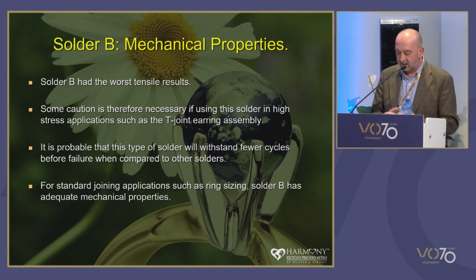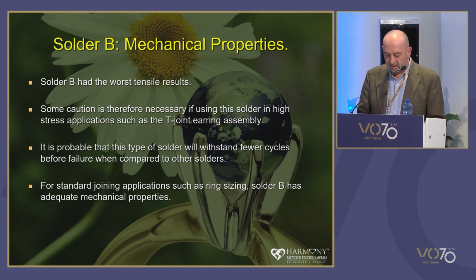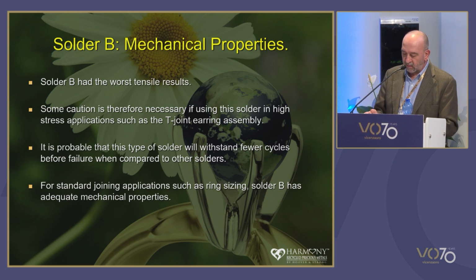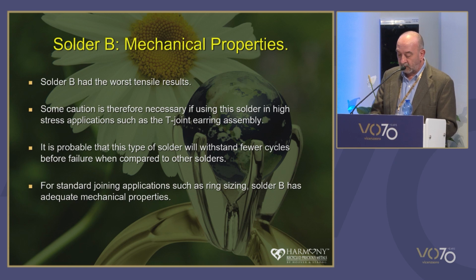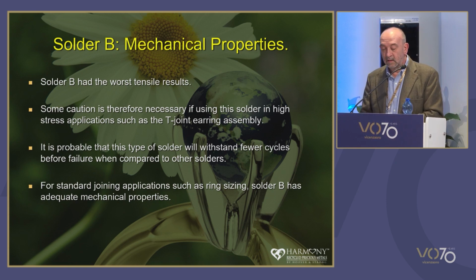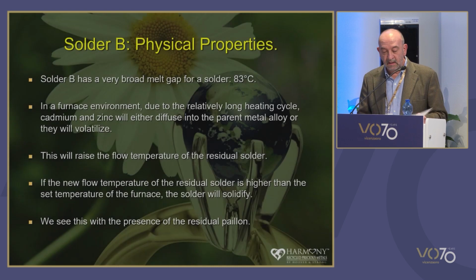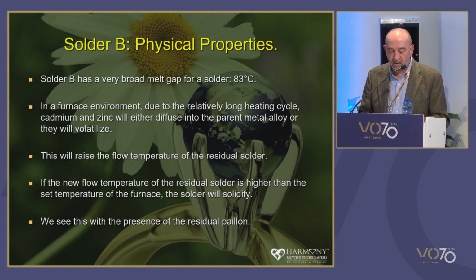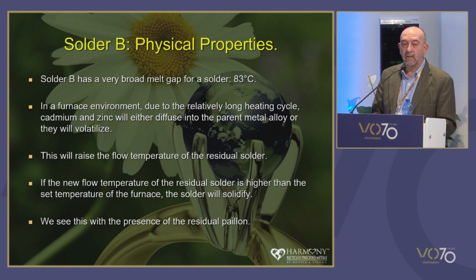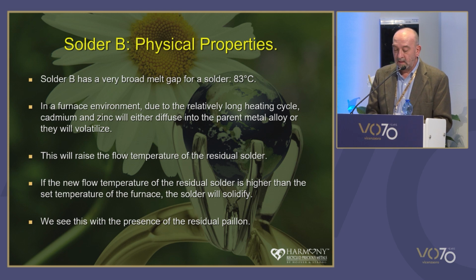It just may need to consider not putting it in a high-stress application. So it's probably not going to be great for ear post soldering. It's going to withstand fewer cycles before failure compared to the other solders. Other properties we can look at. Solder B has a very broad melt gap at 83 degrees centigrade. In a furnace environment, it's going to take a significant amount of time, relatively, to raise the temperature of this solder from melt to flow point.